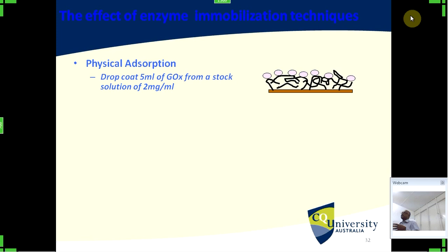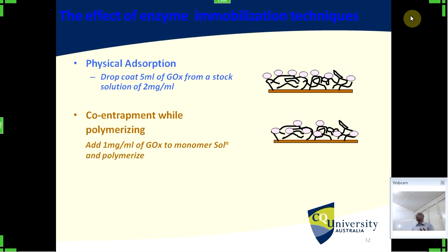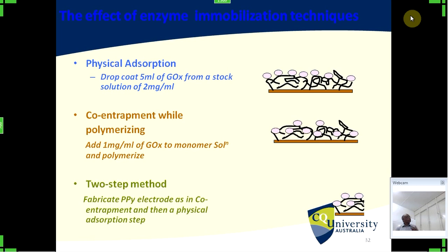Substrate. Now the next part is how to put the enzyme onto that one effectively, so that we can retain more and more enzyme molecules on the substrate material. First one, what we did was physical absorption, just drop casting, and the next one, co-entrapment. We put a little bit of glucose oxidase into the monomer solution and did the electropolymerization. So some of the molecules get entrapped in the chain while it is fabricating. Then add another layer. So two-step method.